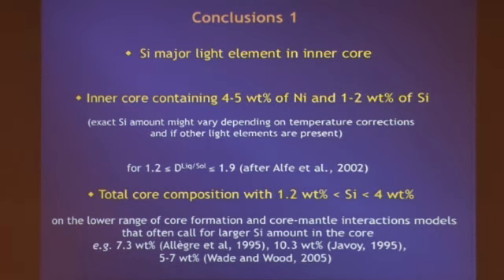So, getting to the conclusion was quick without the figure. The overall evidence from mineral physics measurements on sound velocities supports silicon as the major light element in the inner core. And specifically, we can suggest an inner core model containing 4 to 5 weight% of nickel and 1 to 2 weight% of silicon. Unfortunately, this is not a unique solution because the exact amount of silicon depends on the amount